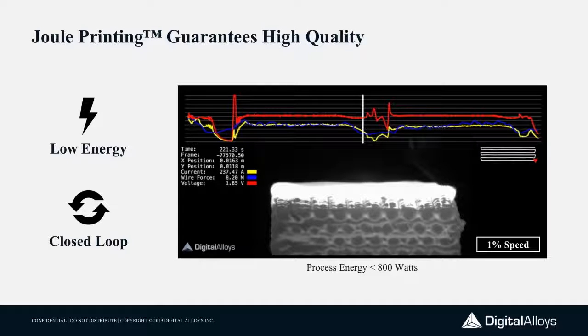And also because this is a closed circuit, we can measure exactly how much energy is going into the melt zone. We can measure exactly how much material is going into that voxel through precision wire feed. And with precision motion control, we know exactly where it is. And so we are able to do really advanced closed loop direct measurement in a way that wasn't possible with most previous metal printing processes.